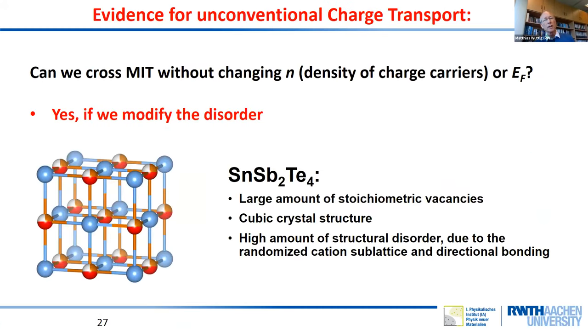So I'm trying to demonstrate that there's indeed evidence for a very unconventional charge transport. And the story I would like to convey in the last maybe 5 or 7 minutes or so is that we can cross the MIT, we produce a metal insulator transition, but without changing the charge carrier concentration. So we don't change the density of charge carriers, but we do something else instead.